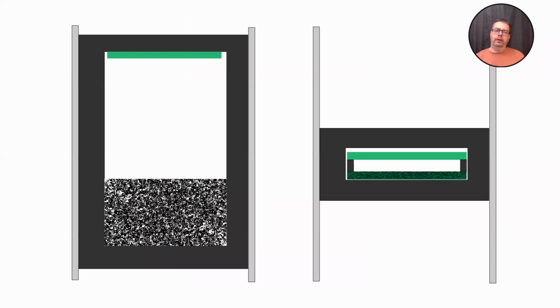And in comparison, on the left side, you see the traditional PVT, and on the right side, you see a modified hot zone for the close-space PVT. And there you have a substrate, you have a source, and this is a ceramic source instead of powder. You decrease the distance, you decrease the growth temperature, you decrease the ambient pressure, and in such way, you can continue to use the PVT principle for growth, but you're learning about the process in a similar way.